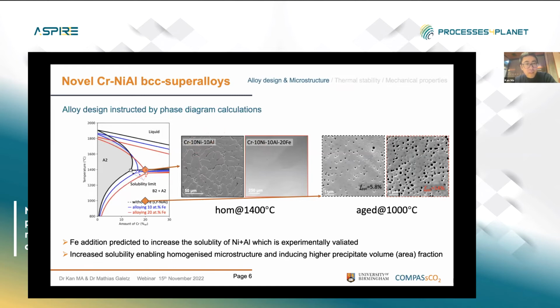And experimentally, as we can see from these two micrographs, without iron, here we form the dendritic microstructure. But if we add iron, we form a quite homogenized single phase microstructure with this beautiful large grain. And also, in these two materials, when we do a lower temperature aging, we obtain this precipitate microstructure, in the quaternary. So with iron, we have a higher volume fraction in our material, which enhances the strengthening of the material.